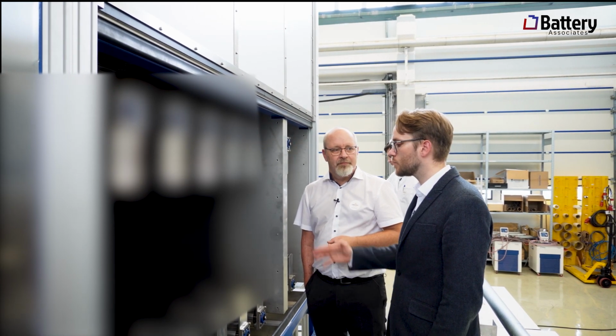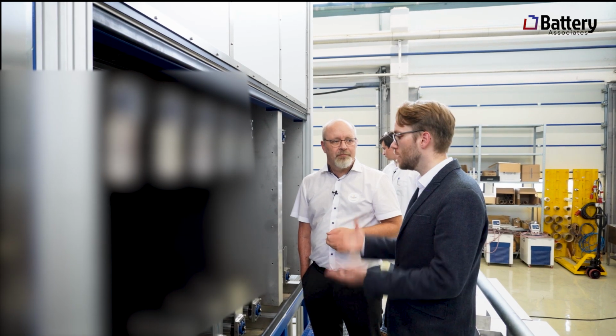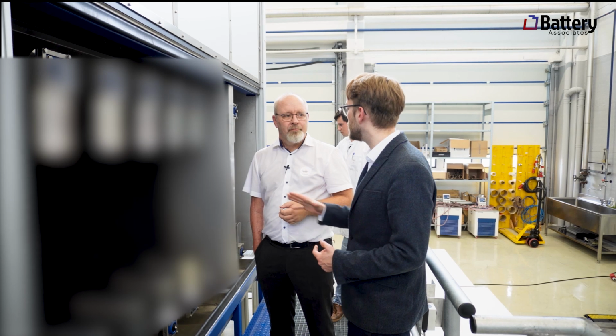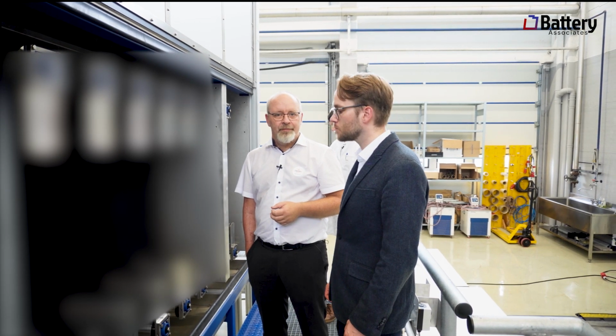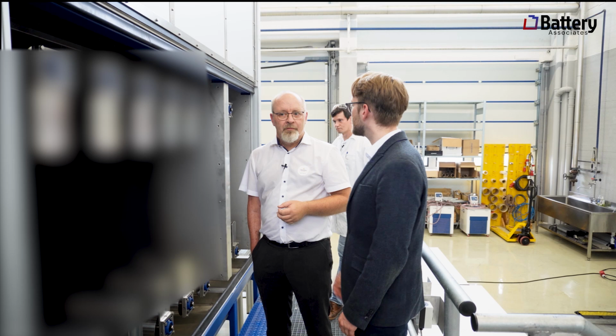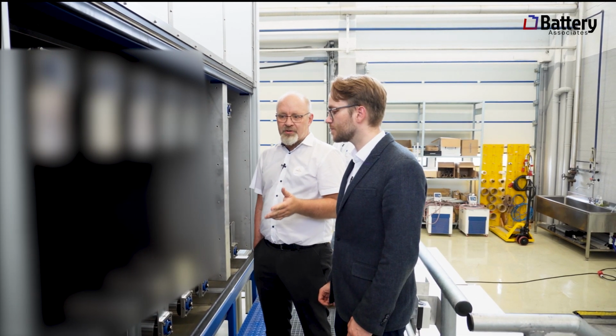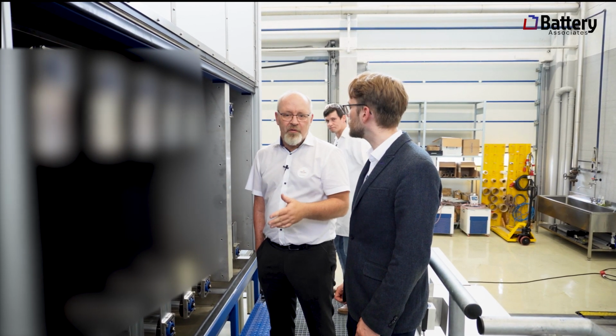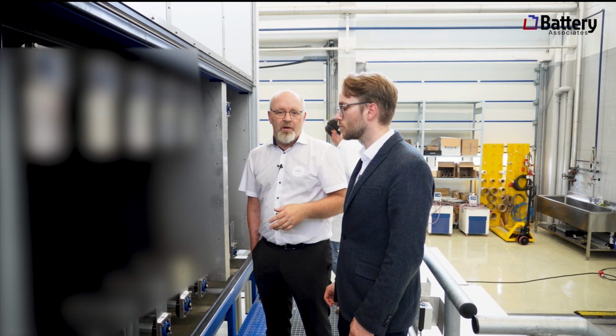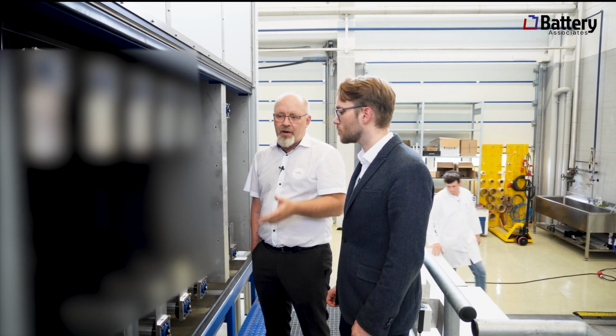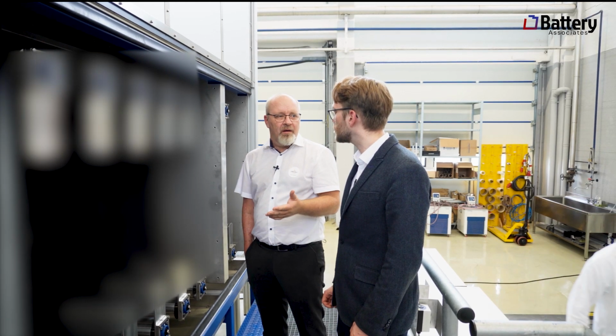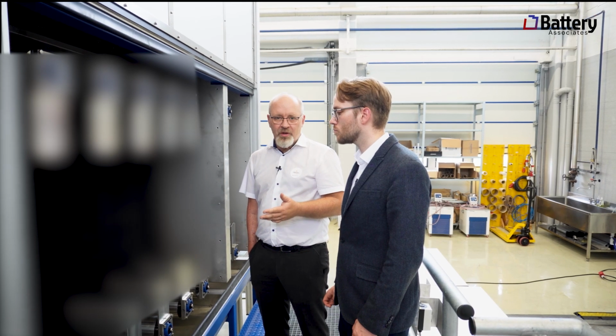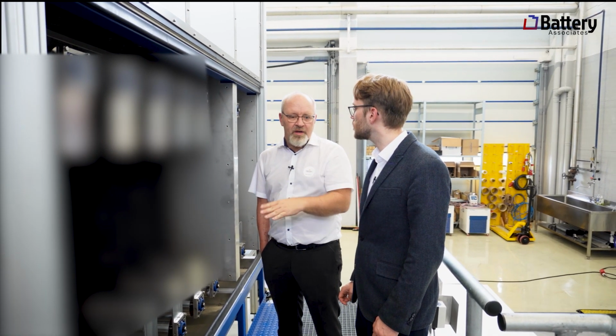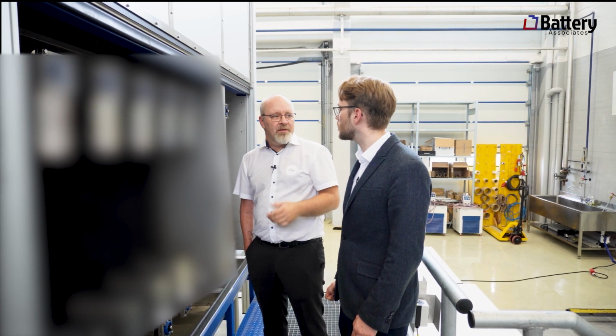Very cool. And is this possible also, because I know some other companies are doing it for the anode side, right? They've got water-based processes. But I think you also mentioned LFP and NMC, so can you also make cathodes this way? Yeah, sure. So why can you do it but not the others? Because we have a freestanding electrode, which has a solid surface right after formation in our first bath, and any winder, any roll does not harm the surface, and that's why we can save such a lot of space here. And in the standard process, you have a sticky surface for almost half of the machine until you can wind it up and down.